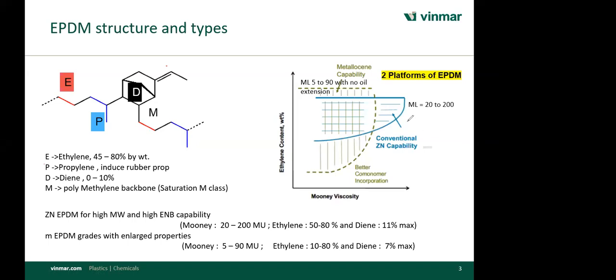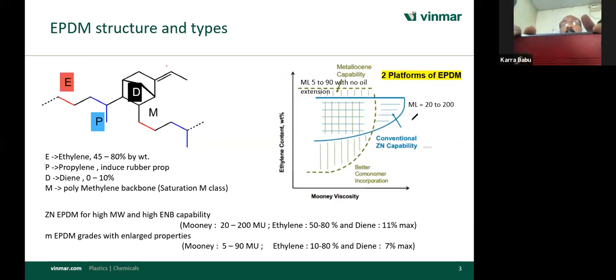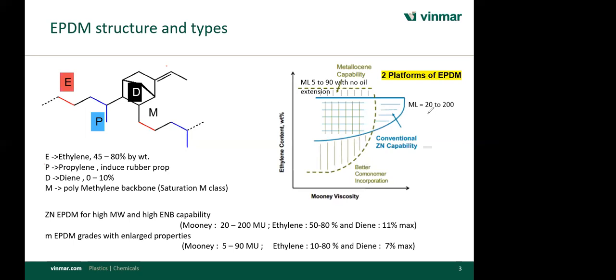If we go with the Ziegler-Natta catalyst, we can get the Mooney viscosity ranging from 20 to 200. Once we go for the higher Mooney, then we go for the oil extended grades. In the Ziegler-Natta catalyst system, we have the capability to produce ethylene content of EPDM 50 to 80%, and diene 11% maximum. But currently, most of the new plants are coming with the metallocene capacity.